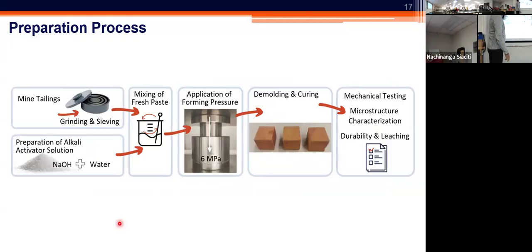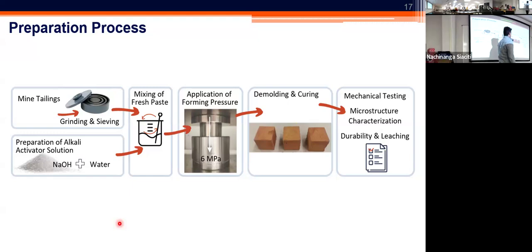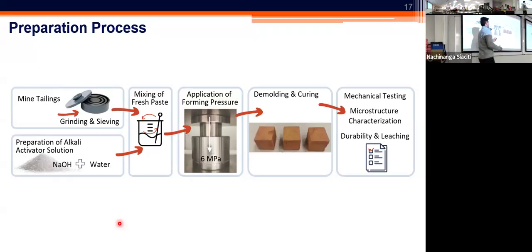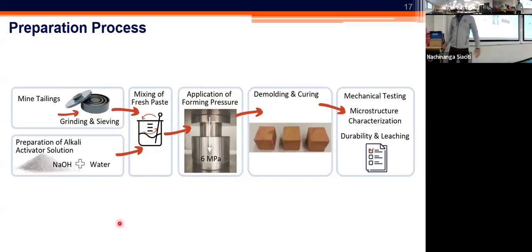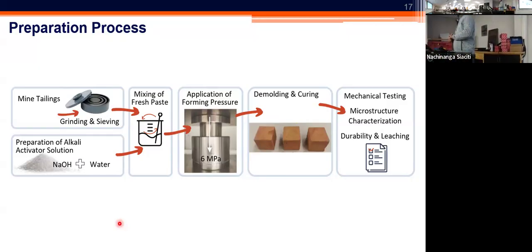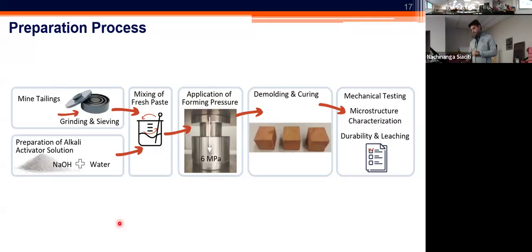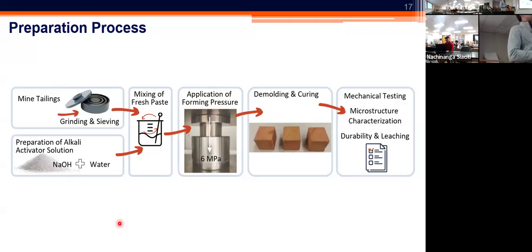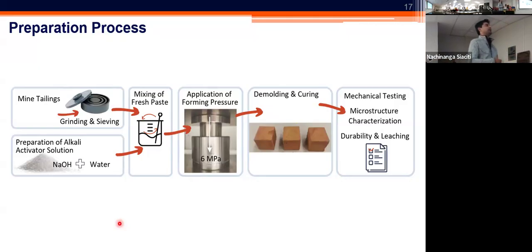But then the process involves mixing of the mine tailings in the solution of sodium hydroxide. Upon the mixing, you come up with a mixture that can be cast inside a form with different levels of application of pressure. And this material can then form these solids. These are initially deformable, but upon exposure to slightly elevated temperatures ranging from 40 to 70 degrees Celsius, you can facilitate the hardening of these bricks, and that essentially results in the formation of the geopolymers. Then you can proceed with the evaluation of different characteristics, including the mechanical behavior, microstructure, durability and leaching performance. So like I said, the process of geopolymerization in the laboratory, at least on the benchtop scale, is fairly straightforward and is well documented and well experimented.